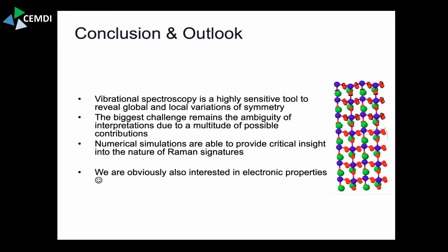There are other activities going on. I know that Alexander is interested in adsorption studies of molecules on the surface, and to see if you can tell from the Raman signature, whether polarization dependent, whether the molecules are lying down or standing up. Oh, nice. In principle, this is something which Federico does. He can actually measure the height, or basically the tunneling current through the molecules. Depending on the population density or the concentration, in the beginning they will probably lie down to minimize total van der Waals forces. But if you increase the concentration, they all want to bind to the surface, and then they compete. At some point, they're all going to stand up so that everybody gets a little footprint. These are things for which Raman spectroscopy is also evolving.